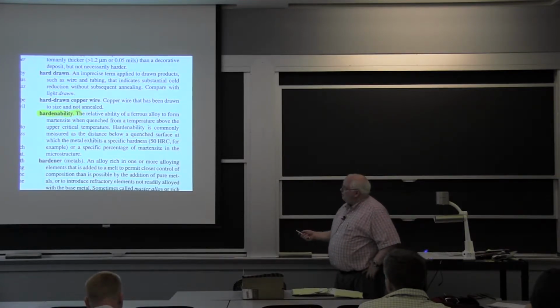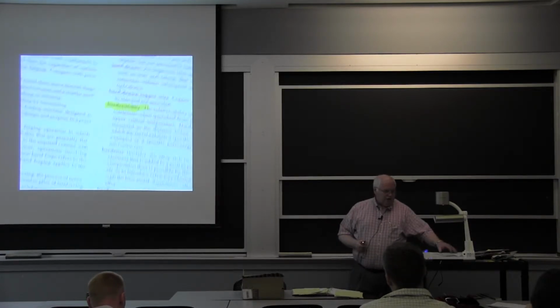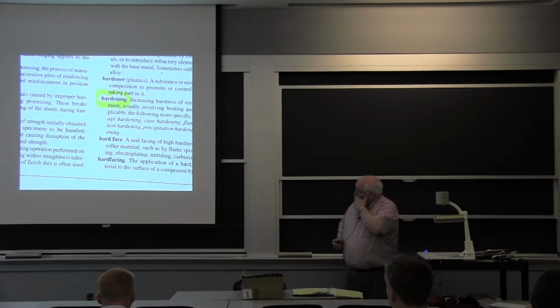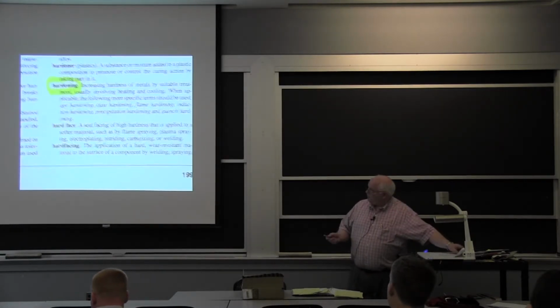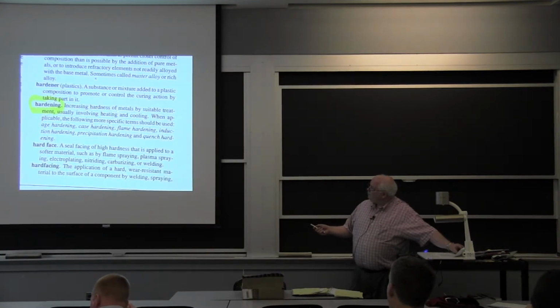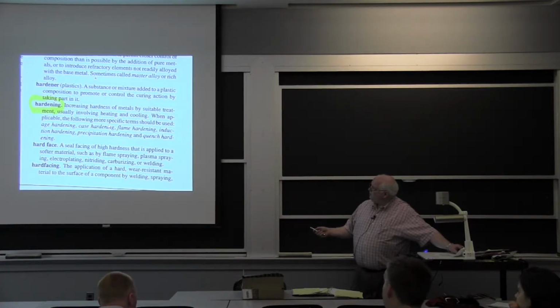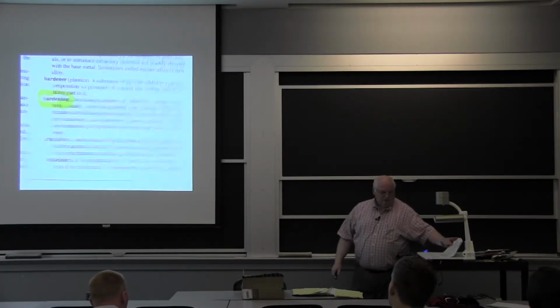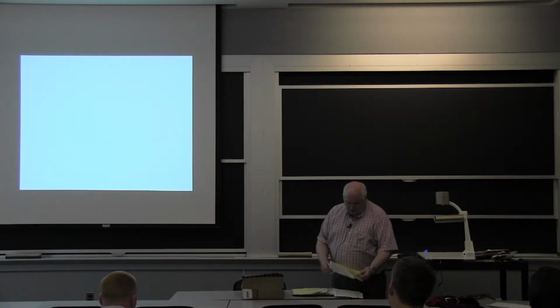Okay, so hardenability is a function, as I showed you, of the carbon content and also the alloy content of the material. Hardening is, you can increase the hardness of a material by various heat treatments: age hardening, which we do with aluminum, flame hardening, induction hardening, precipitation hardening, quench hardening. Steels are quench hardened so far as that goes. So there's lots of ways metallurgists have to try to change the strength of a material. Hardness is a measure of the strength, whereas hardenability is actually a measure of the depth.